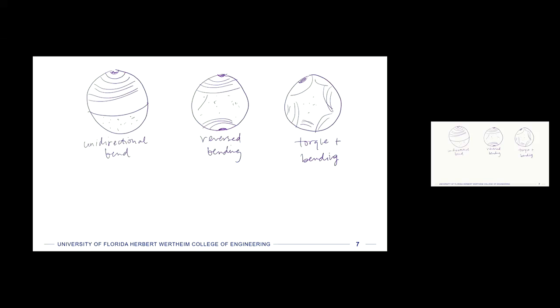I told you a little bit about this at the beginning of the semester, like sort of how does this happen at the nanoscale, right? And so what happens, especially at the surface of a material, as the cyclic stresses happen, is there may be slip, and then those slip bands might protrude out a little from the surface, right? And I talked about characteristic dimensions of these slip bands and how they might actually go back down into the material here as well and pull the material down in, right? So sort of tens to hundreds of atomic lengths in these slip bands that occur at the top of a surface. And so now the surface in a continuum sense does not look like a flat line, but it looks like it's got a defect there,